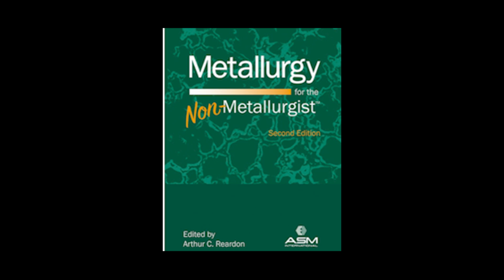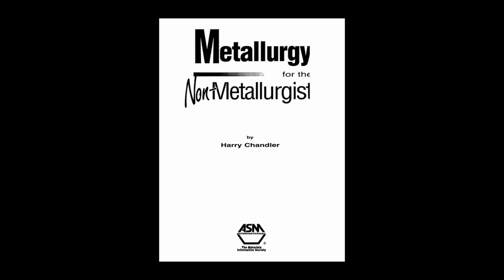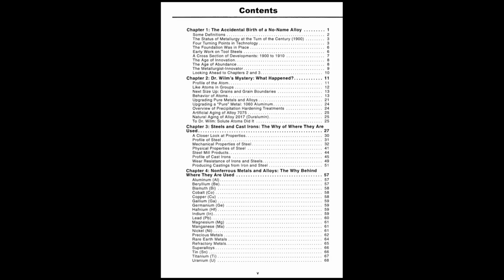And I've heard of cathodic protection. Yes, that's an electrochemical method. You basically force the metal you want to protect to become the cathode, the non-corroding electrode, in the corrosion cell. You can do this either by connecting it to a more reactive metal, a sacrificial anode like zinc or magnesium, which corrodes instead, or you can use an external power source to impress a current onto the structure. Very common for pipelines and ship hulls. So a whole toolkit for fighting corrosion.